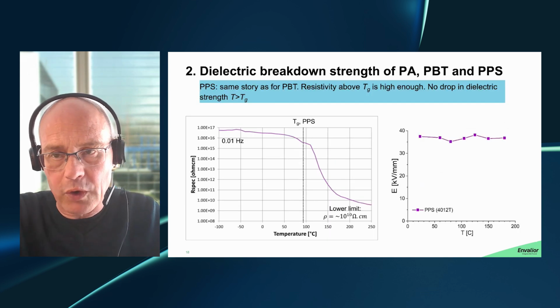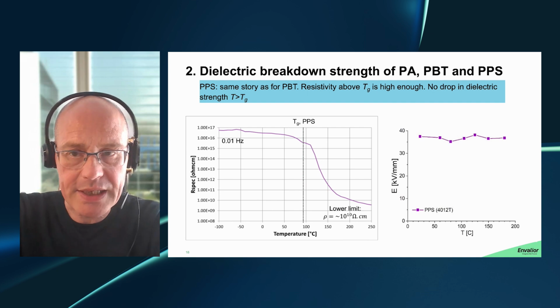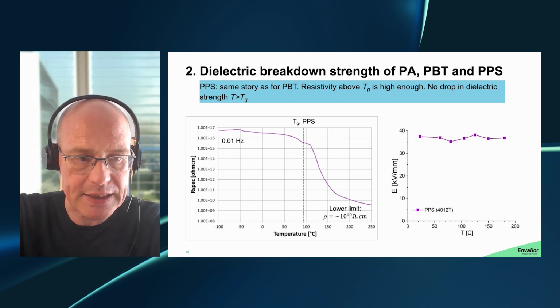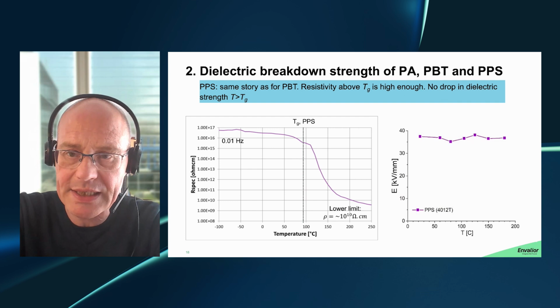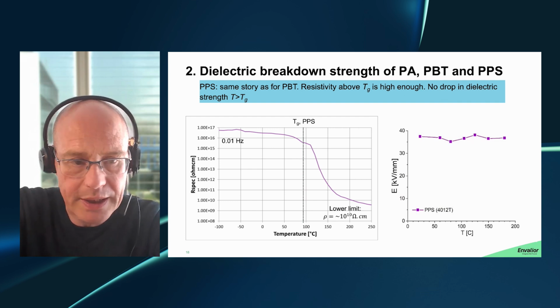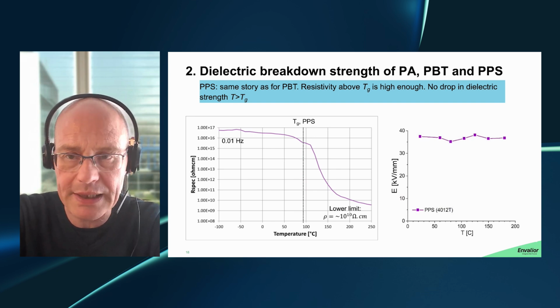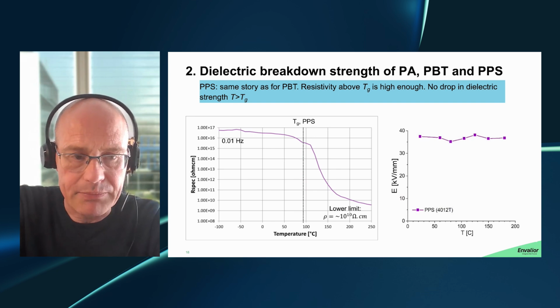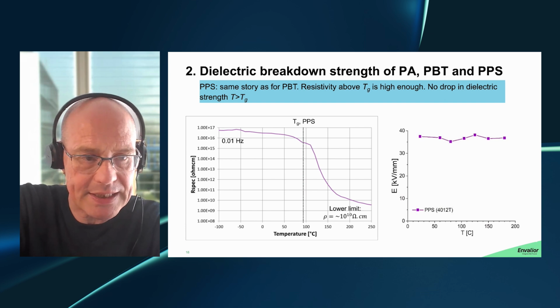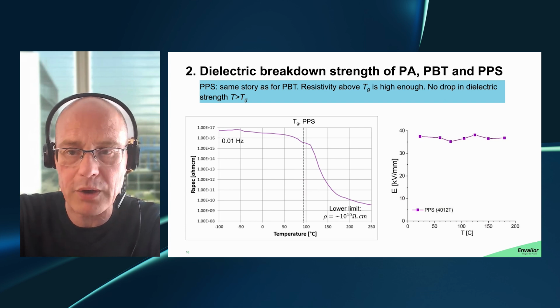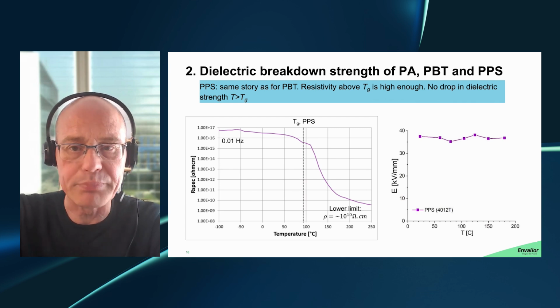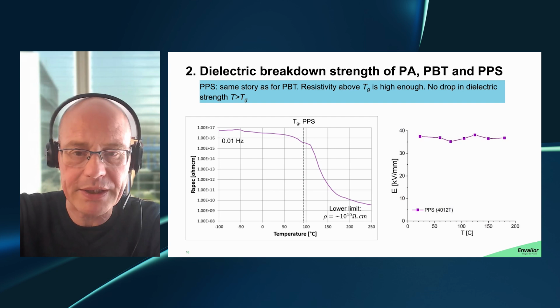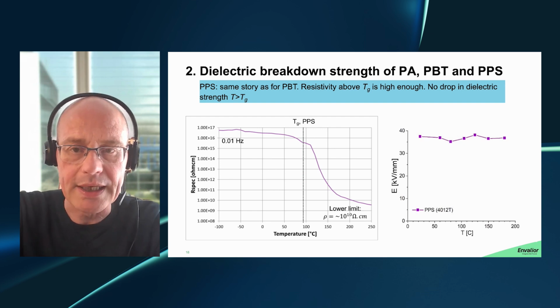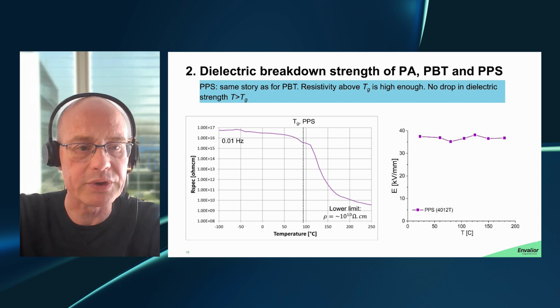Now, for PPS, the situation is perfectly analogous to the PBT case. Also there is a drop in resistivity above the glass transition temperature of your PPS, but the values never hit this, let's say, critical value of 10 to the power 9 ohms times centimeter. So also there, the breakdown strength, as shown in the picture on the right, is guaranteed for all temperatures.